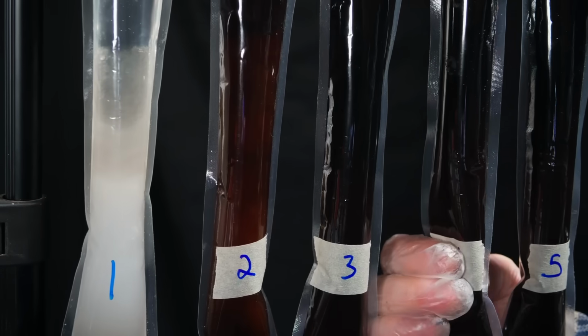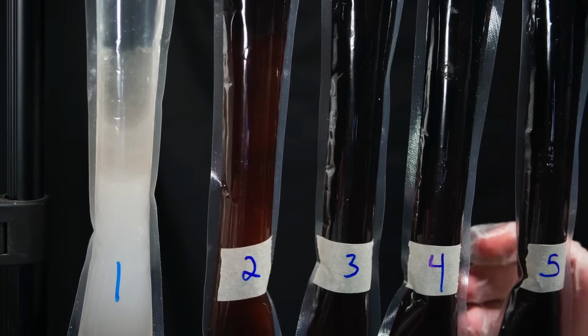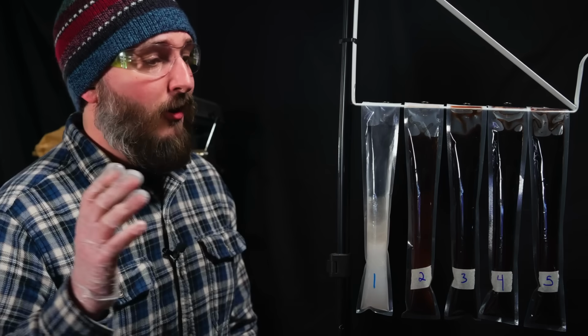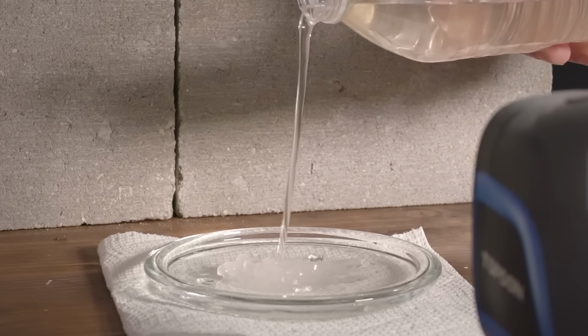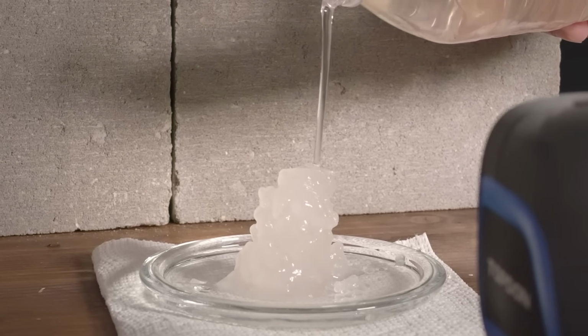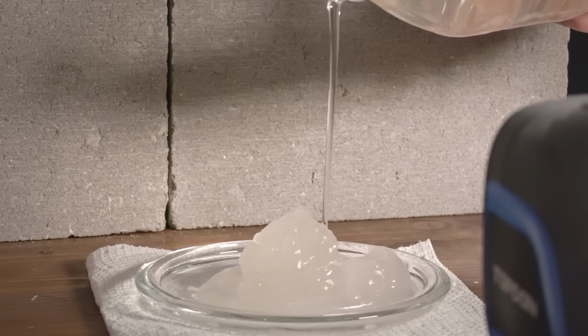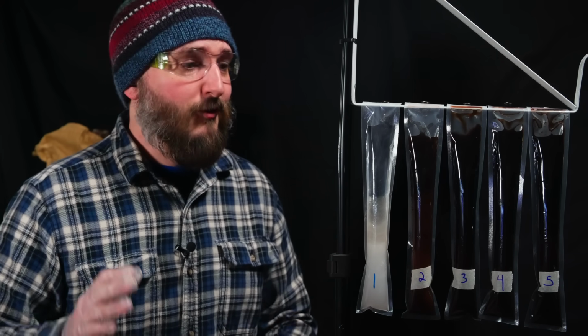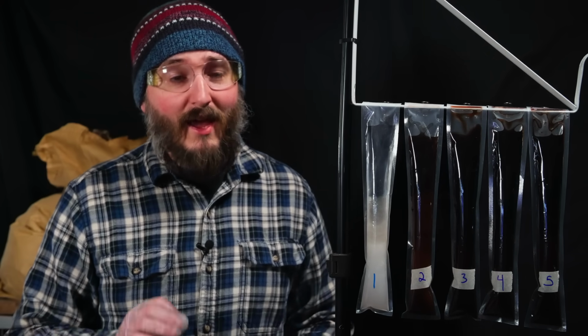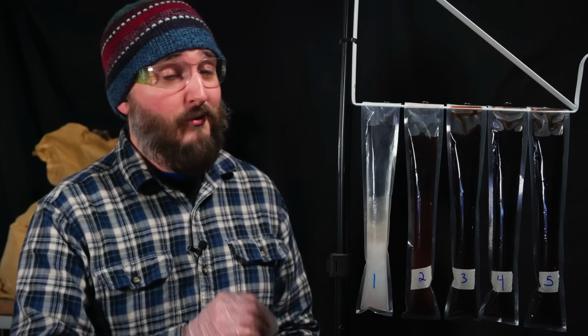The problem with these samples was something I had forgotten about when I decided not to add a thickener for this experiment. All of the samples had crystals on the bottom, and I know it's hard to tell on the darker ones, but they are there. The problem is supercooling, which a thickener would have helped to prevent. Basically, all of the samples cooled to way below their freezing point without actually freezing. You've probably seen the trick where you can do this with water to form little ice towers as you pour it out. Anyways, these PCMs can supercool way more easily than water. And if they get too cold before something actually triggers them to freeze, the salt just can't stay dissolved. There's too much of it, the water is too cold to hold onto it, and no additive could possibly prevent crystals under those circumstances.